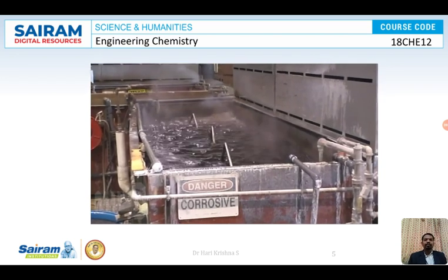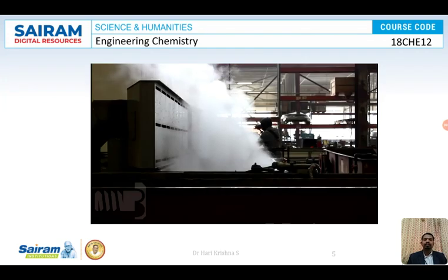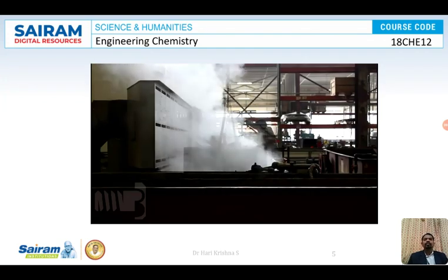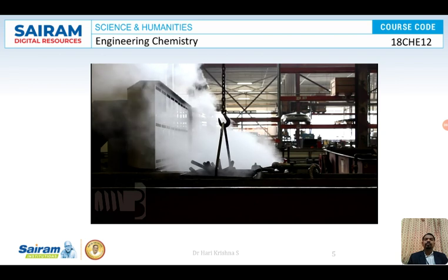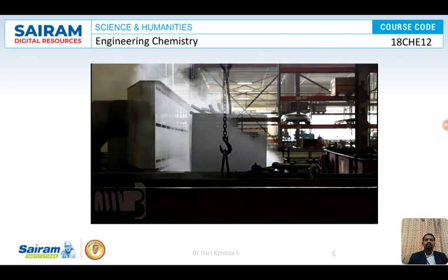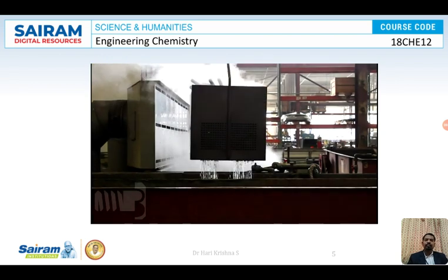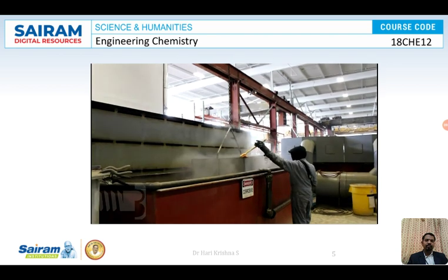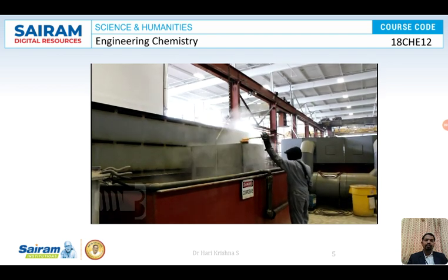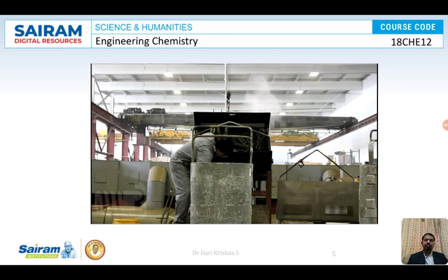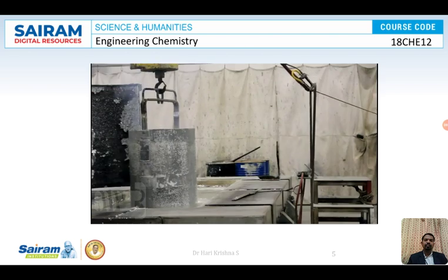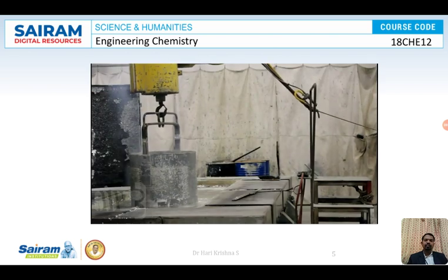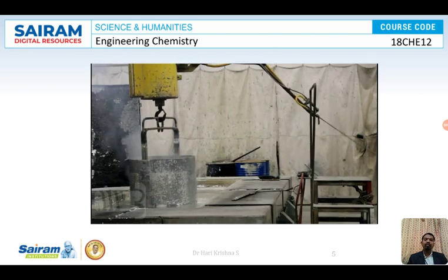The bolts are then submerged in caustic soda, removing any cutting oil. They are then rinsed and submerged in sulfuric acid, which etches the steel so the zinc can penetrate the surface. The bolts are rinsed again, then submerged in flux to facilitate the bond between the zinc and the steel. The bolts are then transferred to baskets or racks and submerged in 840-degree molten zinc for 2 to 5 minutes, depending on their size and grade.